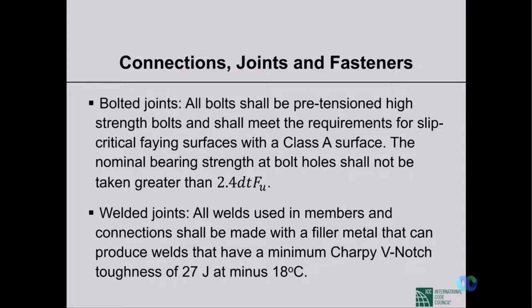For welded joints, all welds used in members and connections shall be made with a filler metal that can produce welds that have a minimum Charpy V-notch toughness of 27 joule at minus 18 degrees centigrade. So we're talking about some tests. The filler metal, the weld metal, has to be tested. And if we have a manufacturer certificate, that is okay. But if it doesn't carry any certificate, then we have to go for this Charpy V-notch toughness test. I think many of you have experience of this testing in the SM lab. We do this testing in our second year, level two.